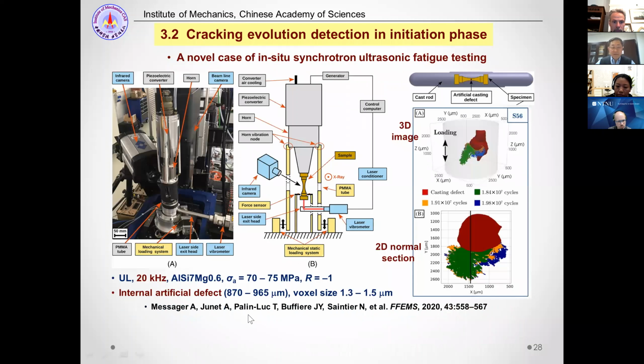And another example is by Professor Palin-Luc's group, and they use a kind of in situ synchrotron ultrasonic testing. The difference between this one and the previous one is they use ultrasonic testing to accelerate the fatigue process, but in the previous one they use a frequency of 400 hertz. So it's a different kind of testing. They use a similar method to detect the small damage evolution process, but I think it is also at the beginning stage. And in this case, they're very clever to use a kind of artificial defect inside the specimen, and to observe the defect evolution or defect development during the loading process.